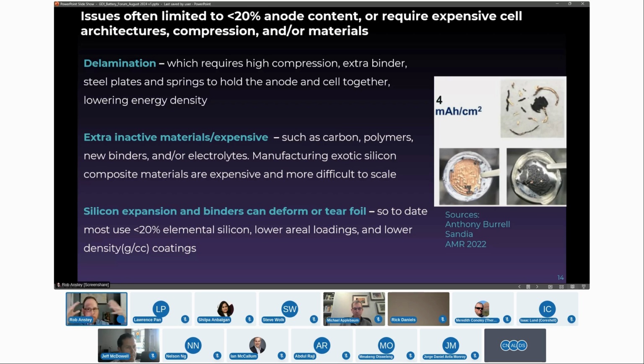I'm still waiting for the commercial cell, the third-party validated data, to see how they do that. Some of the ways they do that is by using a lot more polymer, a lot more binder, carbon nanotubes, carbon nanostructures, pre-lithiating the silicon before you put it in. That helps a lot. If you can pre-lithiate the material before it goes into the mixing and the coating, that actually helps with the expansion. But then pre-lithiated material has a much shorter shelf life and reacts a lot more during the mixing and coating. So that has its own issues. And then ultimately, you will have to look at all these different things.